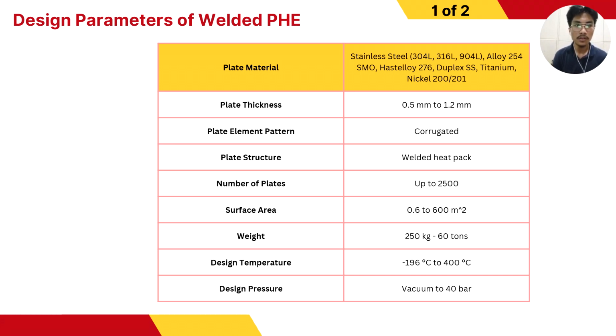So it is also dependent on a number of reasons or factors. This includes the types of working fluids, as well as the working conditions, the temperatures and pressures. So when we have 1 megapascal pressure, the corresponding plate thickness is going to be 0.5 millimeters. And if having more than 1 megapascal, 0.6 millimeters and above should be used.